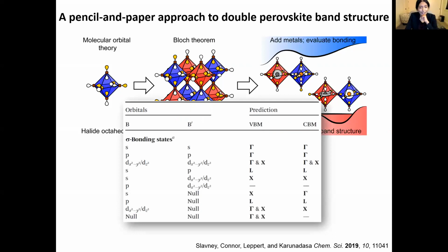And by doing this, we are now in a position to be able to predict, if we were simply given a composition and we were told these are your two B sites, we are able to predict with a fairly high degree of accuracy whether the material will have a direct band gap or an indirect band gap. So all we need to know are the frontier orbitals of the two B sites. And that tells us the valence band maximum and the conduction band minimum.